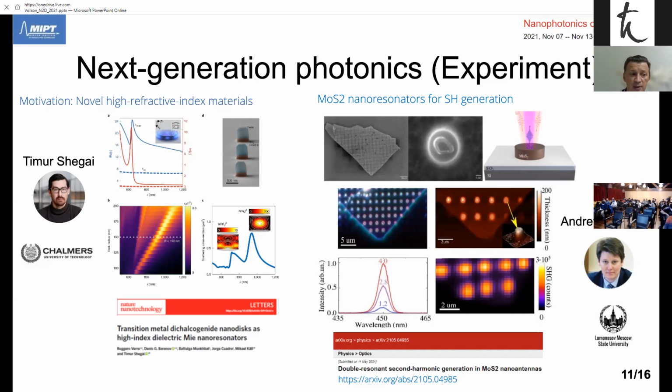These nanodiscs were studied by second harmonic generation rotational anisotropy, revealing the retention of crystallinity and orientation of the crystallographic axis of the single disk structure after fabrication.